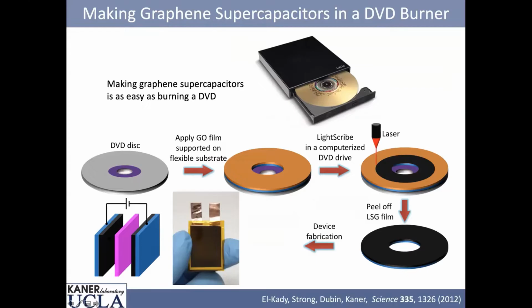But supercapacitors are a bit different than batteries. Instead of an anode and a cathode, we have a positive electrode and a negative electrode. When you charge this up, the positive electrode takes on negative ions, the negative electrode positive ions. Because they're already there, they only move atomic distances, and so you can charge this in seconds.